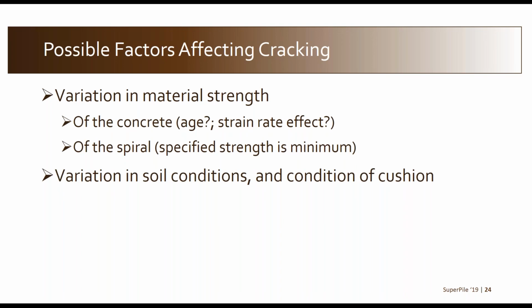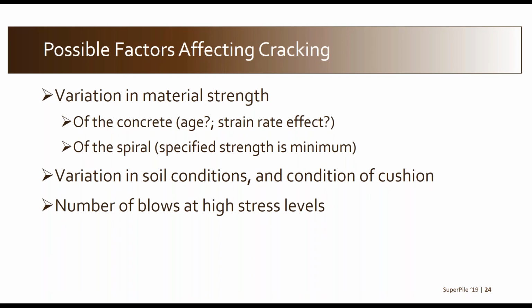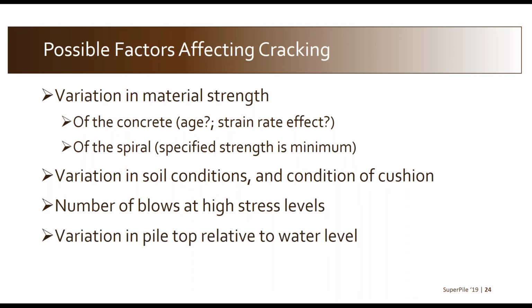We do know there's variability in the ground conditions across the site, although we weren't able to pinpoint anything specific about the location where the damaged piles seem to be clustered in terms of the ground conditions being different there than at the other groups. Although that may have just been, frankly, from a lack of adequate data to characterize the subsurface on that refined of a level. The condition of the cushion, of course, is influencing the maximum stresses experienced by an individual pile and how many blows an individual pile is subjected to at the maximum blow count. And of course, where it sits relative to water.